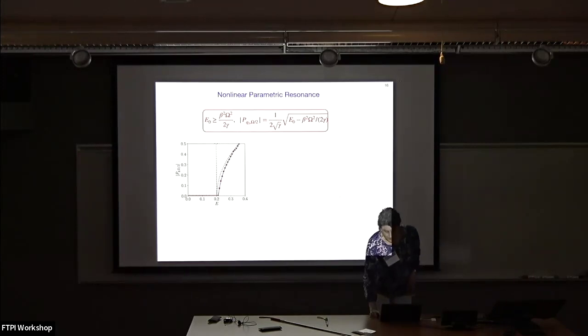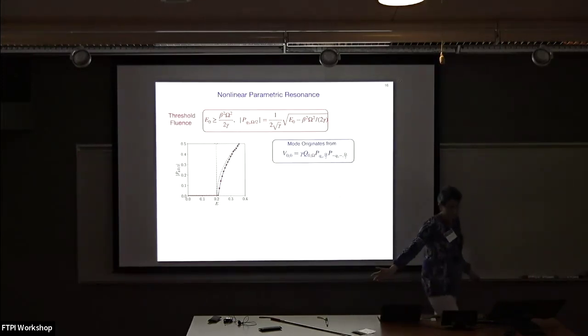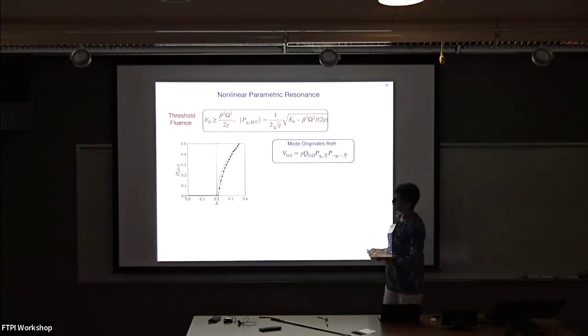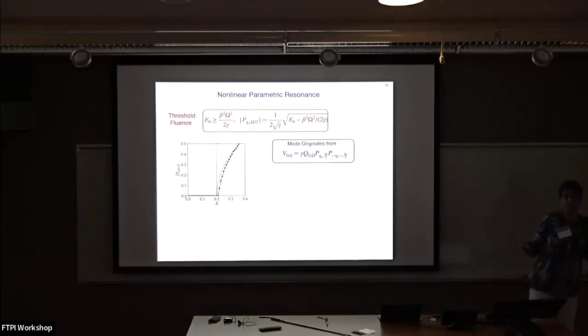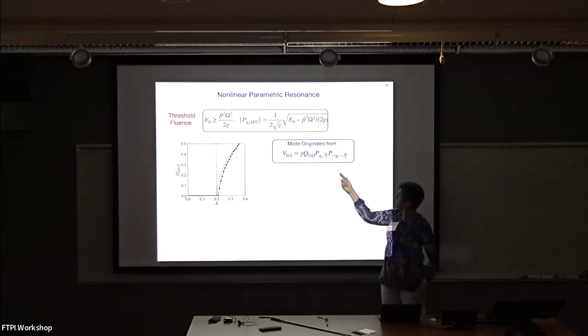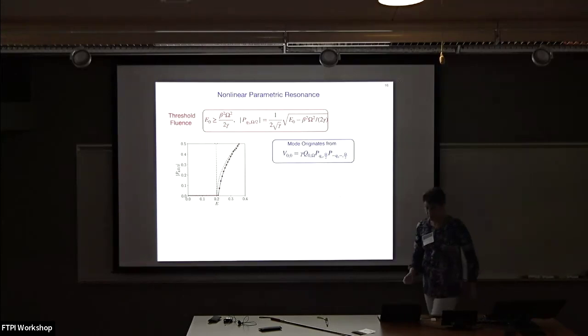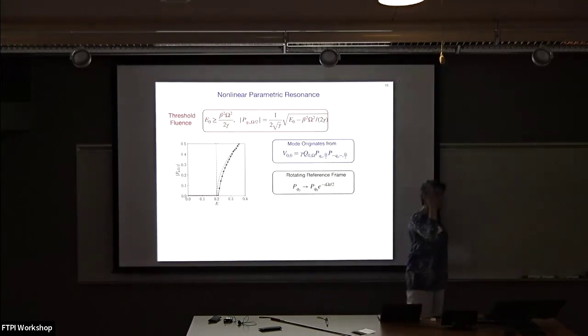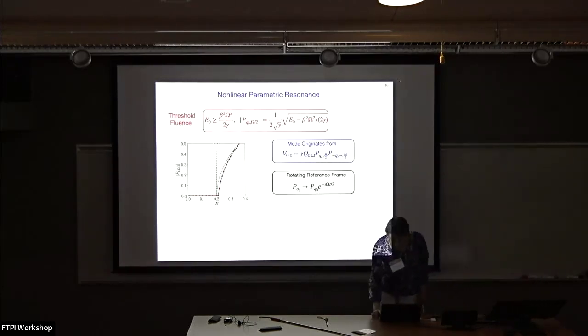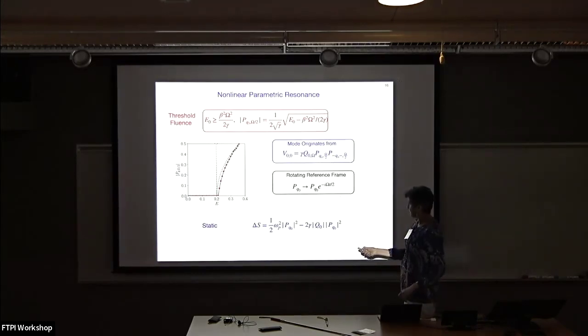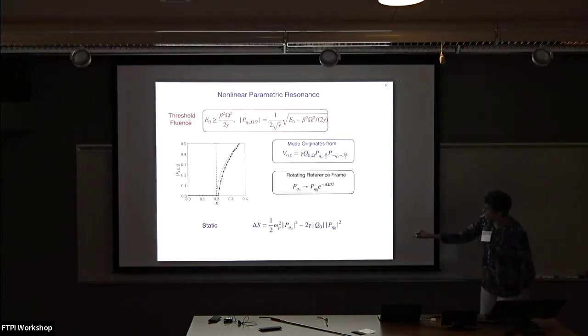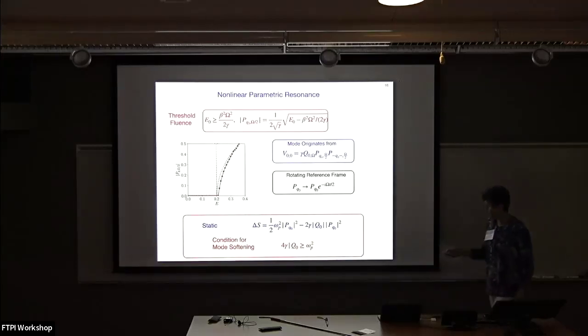Now, you might say, wait a minute, you have a new mode. It originates from this vertex. What kind do I have? A mode softening? What's going on here? And in fact, what you can show is this vertex should couple to the static mass. However, I have to go into a rotating reference frame. And in a rotating reference frame, I get the static term. And you see that this is my first term, this is the bare mass, but here I have this other term. What that tells me is that I have a condition for mode softening, which again, not surprisingly, tells me about the importance of the amplitude of the resonant drive and the nonlinear current.